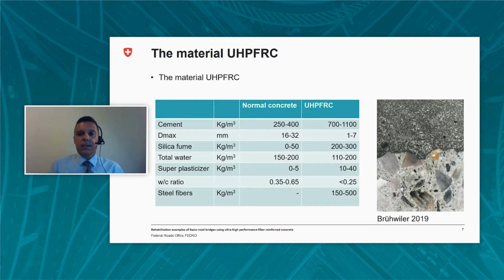It contains silica fume, which fulfills 3 functions. It fills voids between cement grains, it enhances their rheological characteristics, and it forms hydration products by pozzolanic activity. Thus, the mechanical strengths are increased and the microstructure and compacity of this material are enhanced.